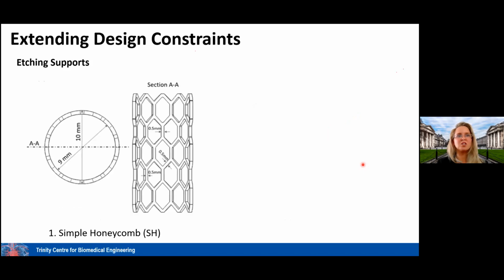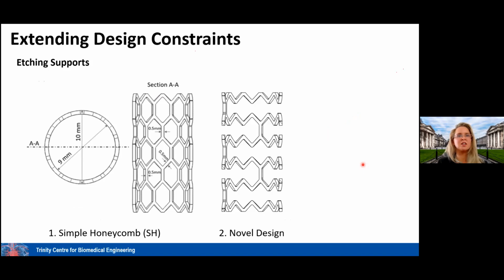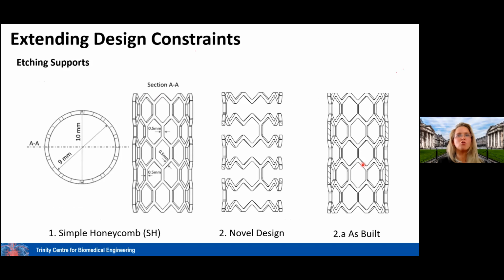So I said, what can we do? Well, if we can remove material, then perhaps we can put supports in and have a honeycomb type structure, as you can see here, but ultimately through etching, remove those supporting structures. So you can see here we make some of the struts thinner, so really they're only acting as supports. They're not actually part of the stent design. We expect to remove these in our etching procedure. So that's how we will go from our as-built here, keeping with additive rules, to getting to a much more complex stent structure. So let's see how that works.